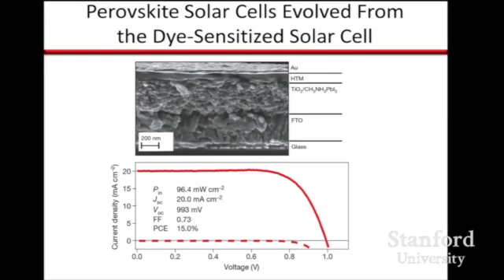Originally, it was used as a replacement for dyes in a dye-sensitized solar cell. You'd have a nanoporous film of titania, and then you'd fill it with the perovskite. And on the bottom, you'd have an electron withdrawing contact, and on the top, you'd have a hole withdrawing contact. This works well. You can get 15% efficiency.